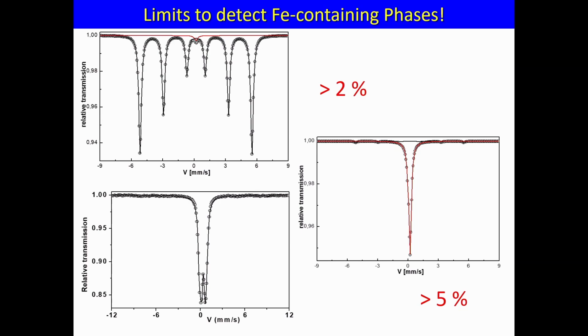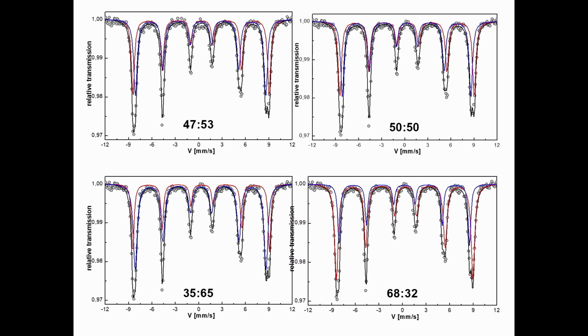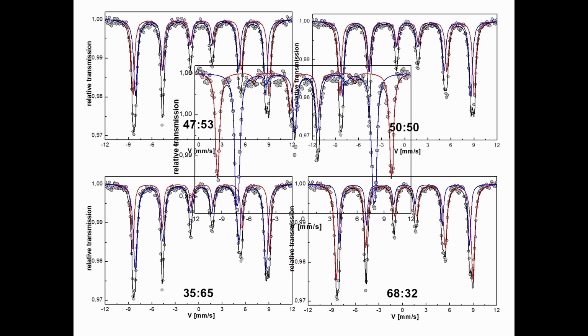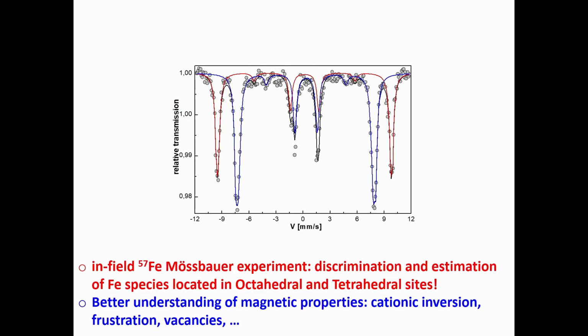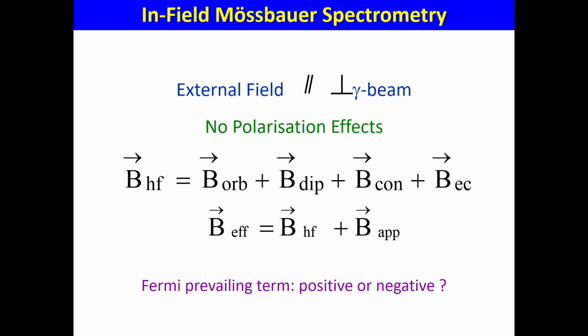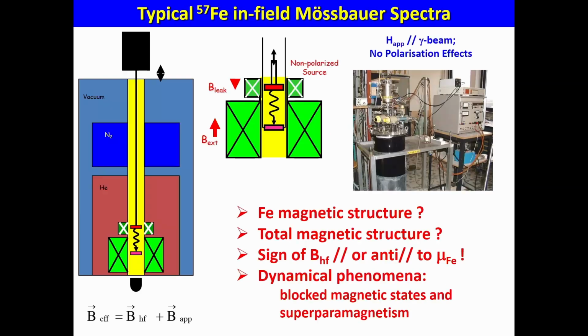Okay? Or sometimes what you can do, because of course here you have a pure doublet, but if you zoom on the baseline, you can see some structure. So you can extend the scale on the baseline. Sometimes you can see something. So I repeat this figure. If you go down versus temperature, there are no more changes, except an extension of the hyperfine field. But you will still get the lack of resolution. So what to do is to apply an external magnetic field. We will see here. You have to know whether it is perpendicular or parallel to the gamma beam. You know it. No polarization effects. So I will explain this.